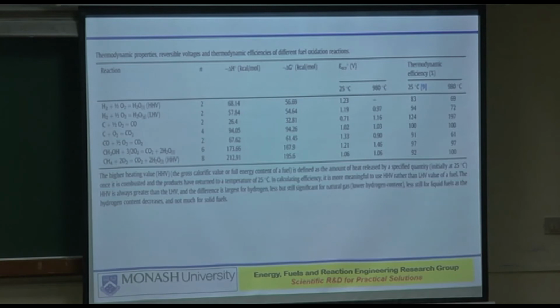We looked at reforming of methane, I think yesterday. Do you remember what temperature? No, before that. So we're looking at about 900, 1000 degrees or so. But in a fuel cell, if you have an internal reformer, and if you can also put a catalyst there, then internally you can reform it with steam. Steam is needed, or CO2 is needed. We have seen that yesterday. You can do it at a much lower temperature, about say 650 or so.